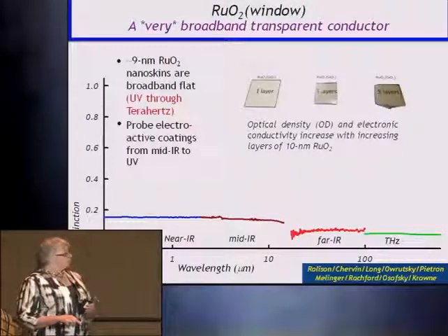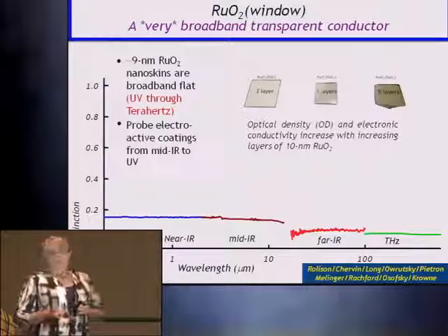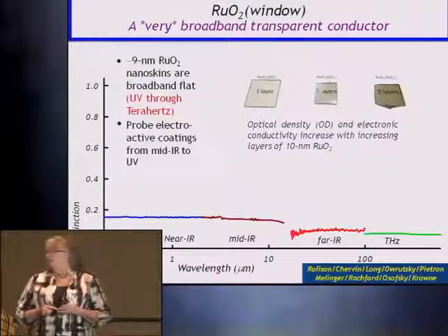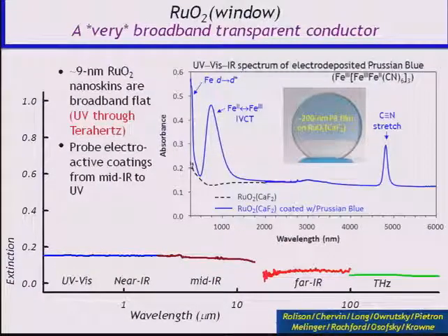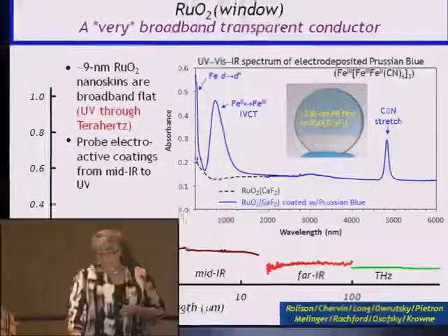And as we have studied this over an extremely long wavelength range, it's broadband flat, from the terahertz to the ultraviolet. That's very hard to accomplish with almost any other electrically conductive, transparent window. So Jeff could take calcium fluoride coated with a skin of the RuO2 and electrochemically deposit Prussian blue, and on our Cary, which goes from ultraviolet to near IR, see the intervalent charge transfer, which gives the color, see the d to d* for the iron in the ultraviolet, and see the nitrile stretch in the near IR. We're actually pushing this out to microwave now. So we now have a pretty good conductor that is, as we like to say, DC to daylight transparent.